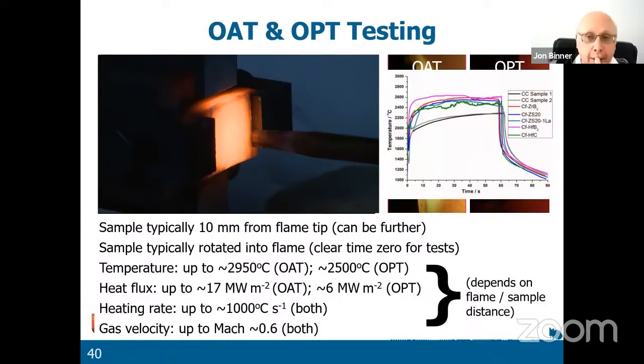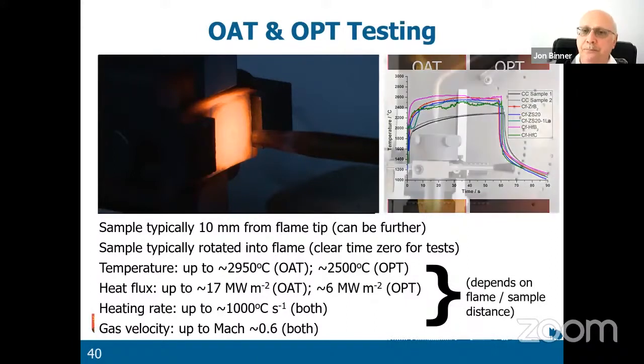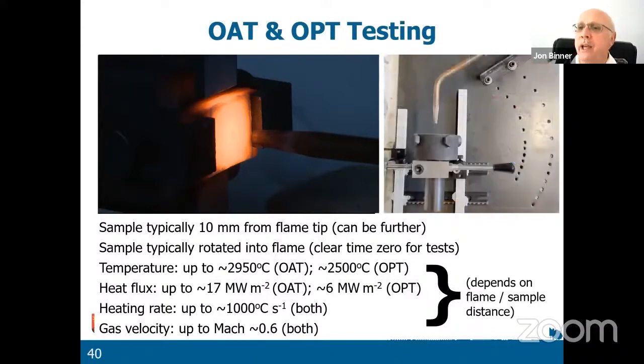And there you can see a whole series of heating rates and different materials will have different heating rates because of their different thermal conductivity. We've also developed the process where we can now do it at 90 degrees, which is where we started, but also, as you can see, we can move the torch around. So now we can have angles varying from almost 0, about 5 degrees, right through to 90 degrees. So we can investigate the effects of a glancing flame on the surface.